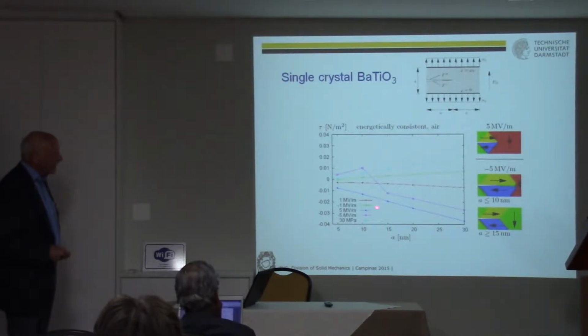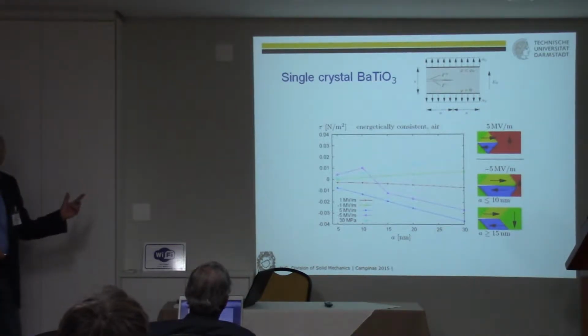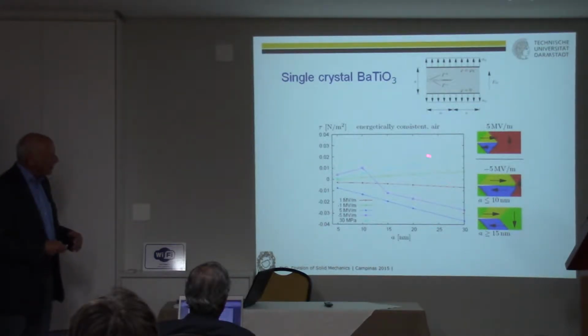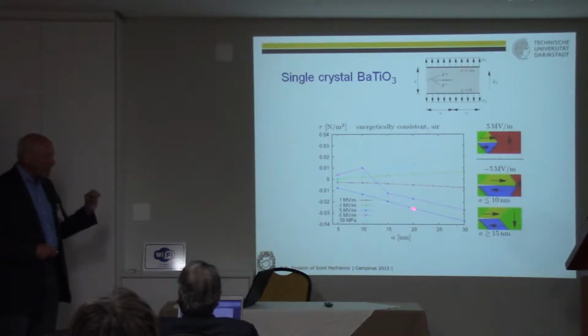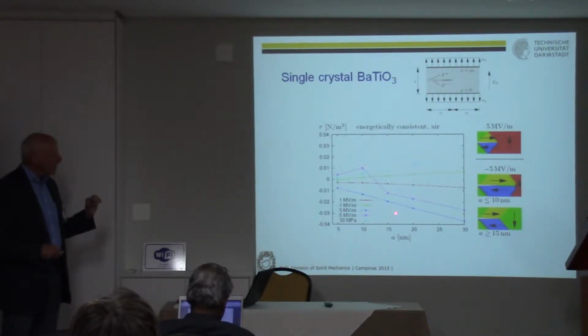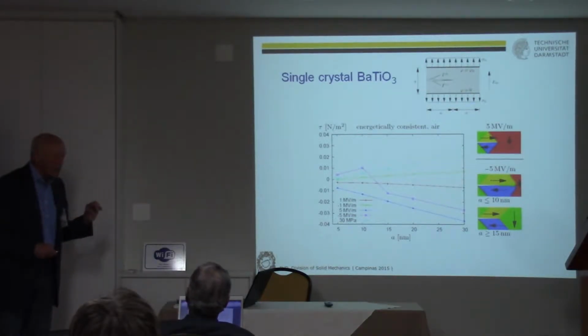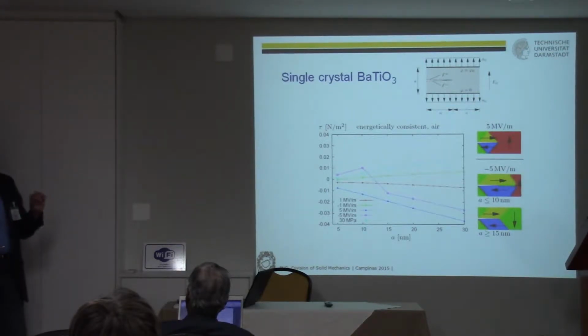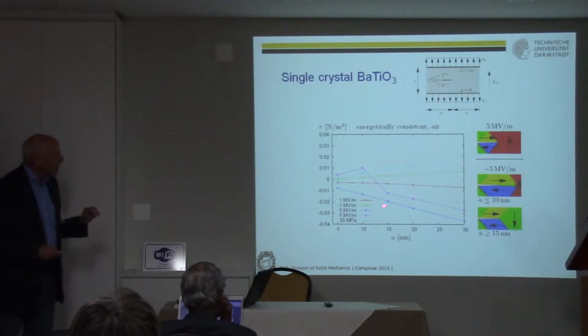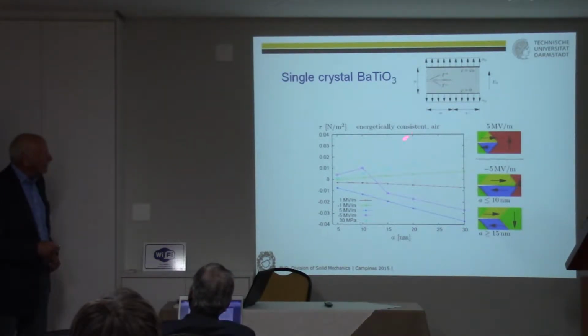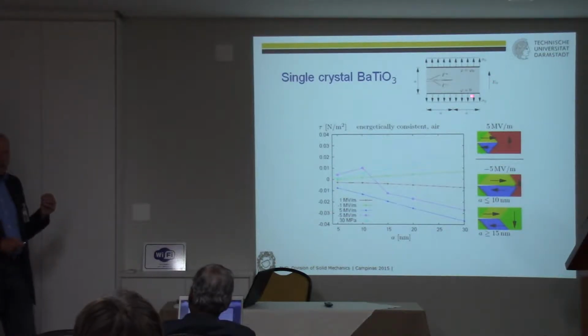And the result was such that there were big differences between the old calculation and the new calculation, and which one is the correct one? Of course, because these material constants stem from MD simulation and micromechanical experiments, we now say, okay, this really can be used for simulations in the nanoscale. And what we now saw was that the results really depend on the geometry of the structure. So you have really a scaling problem here.